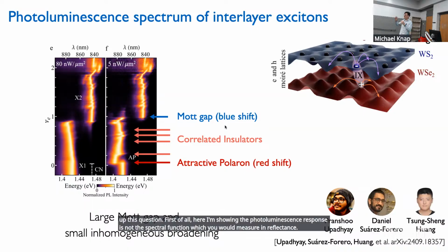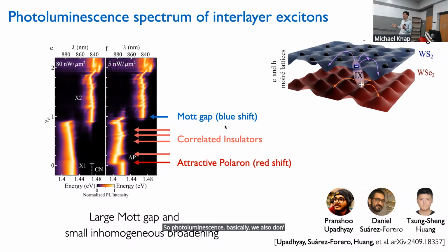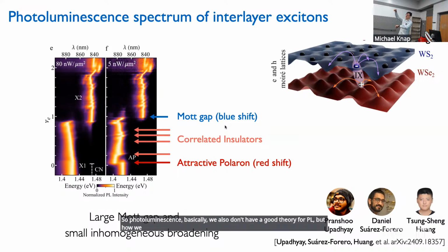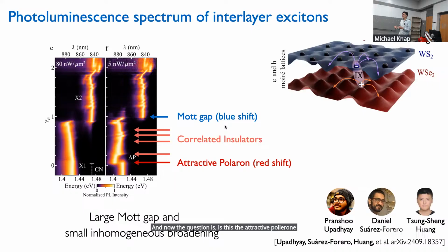For photoluminescence, we also don't have a good theory for PL, but how we envision it is that you shoot in energy, everything is drizzling down to some metastable state, and then in the end you collect the light of the decay of this metastable state. So this would mean that I'm going into the lowest optically active state. This is what I'm seeing in PL. And now the question is, is this the attractive polaron or the trion? This is very subtle. We do not know in general. It could be that this is the trion response, but at the moment we need to think about how to distinguish these two responses.